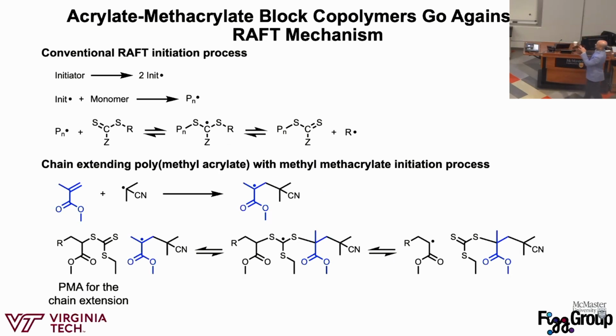All right, so I want to go back to this idea of the initiation process and the propagation process just to ground us in chemically why this is so hard to do. So this is the conventional initiation process, which I'm going to use to guide us through a conventional chain extension and why it's hard. So if you were doing a chain extension of methyl acrylate with methyl methacrylate, and we look at this conventional initiator, if this is AIBN, we're going to get an AIBN fragment, which I have shown here. What we want to do is chain extend this polymethyl acrylate with methyl methacrylate. So if you're just doing this in a conventional RAFT polymerization, you'd get this AIBN fragment. This is going to react with methyl methacrylate monomer in solution just based off concentration of things in solution. So any conventional chain extension in RAFT, you're going to get a small oligomer of the second block, like a small homopolymer of the second block, regardless of what you do.